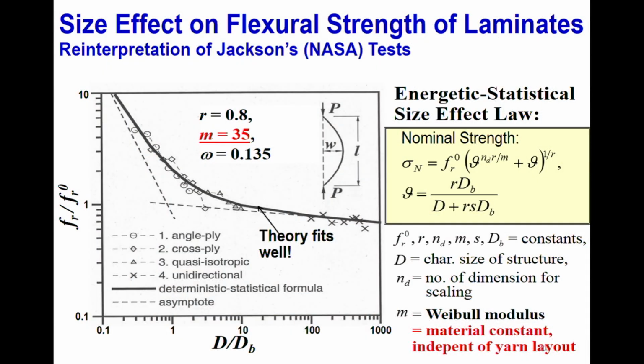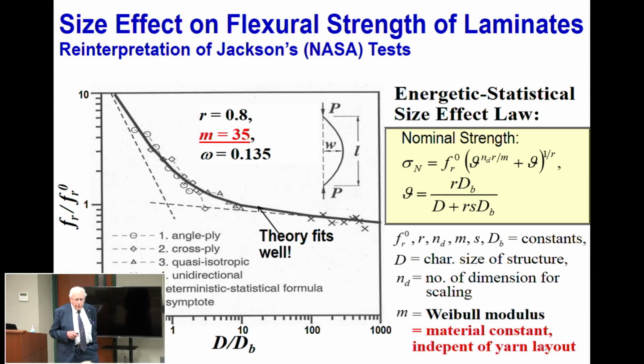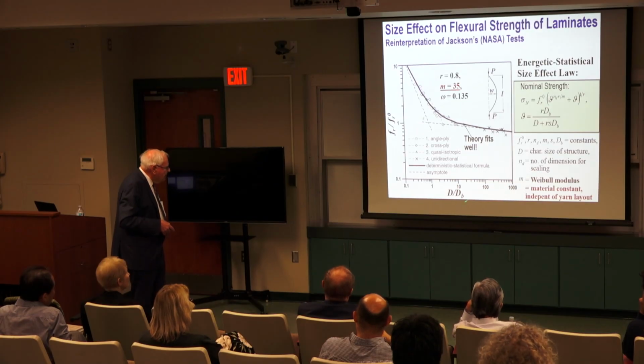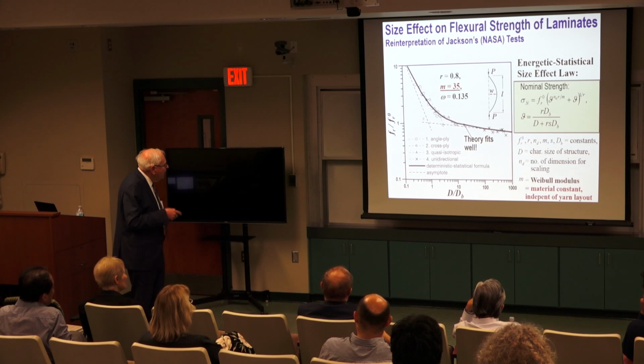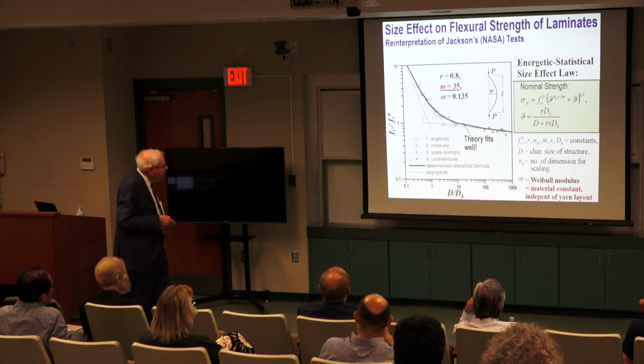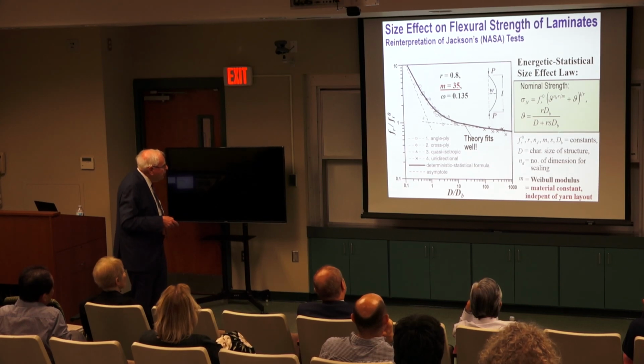This is a set of composites from NASA, where they concluded in this testing by Jackson that Weibull modulus is variable, that it depends on structure size and structure shape. Impossible. That's a material property. That's denying even boundary value problem and so forth. But we of course have to normalize it for different materials, which have different constants here, but it perfectly agrees. I don't say it proves, but no disagreement. We can perfectly fit all this with one Weibull modulus and with zero threshold. And you can even find a formula, an asymptotic matching formula, which describes that.